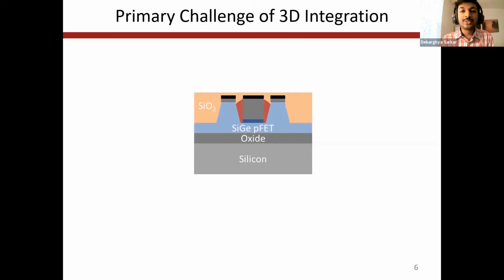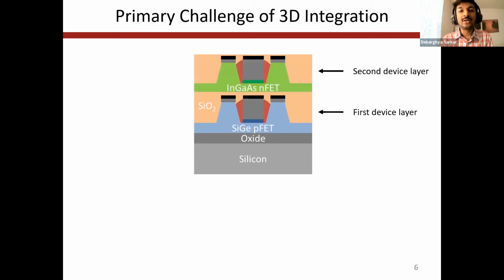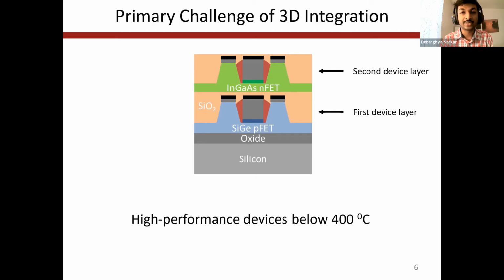Now, one of the primary challenges associated with 3D integrated circuits is, assuming the first device layer is already on the chip, how to integrate the second and higher layers in order to get high performance devices in these top layers at a temperature below 400 degrees Celsius, so that the underlying active layers are not affected. And this has been the holistic challenge that my PhD research has tried to explore.